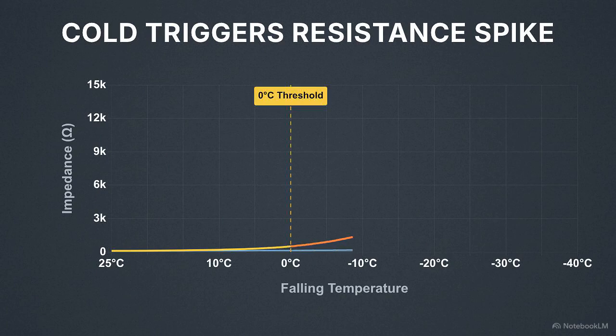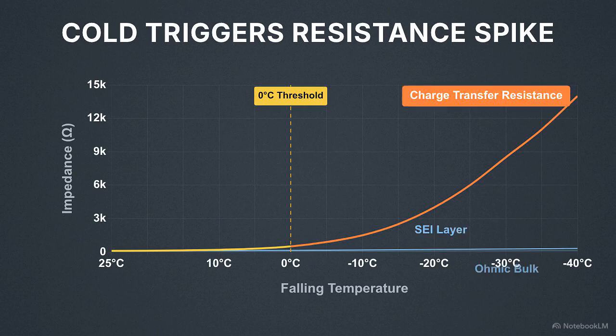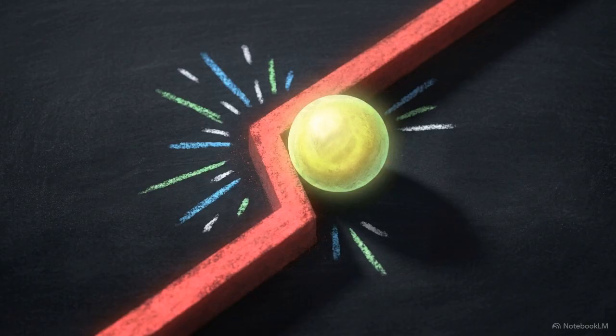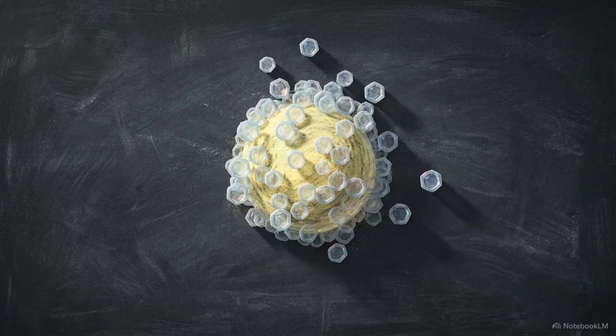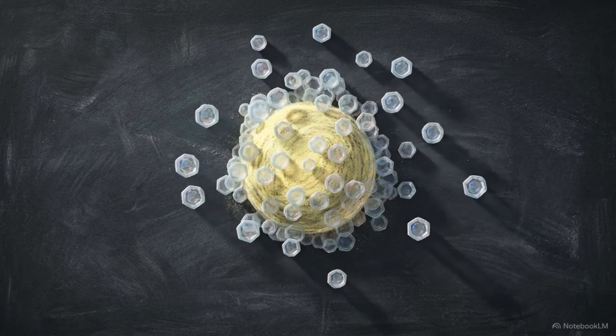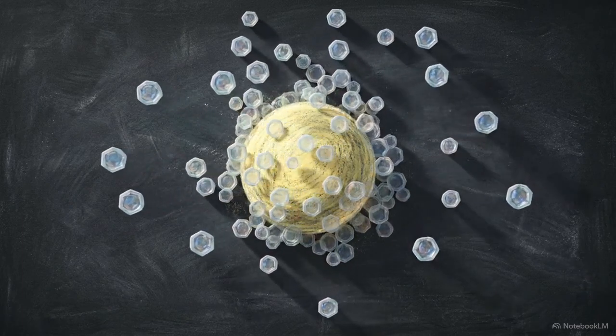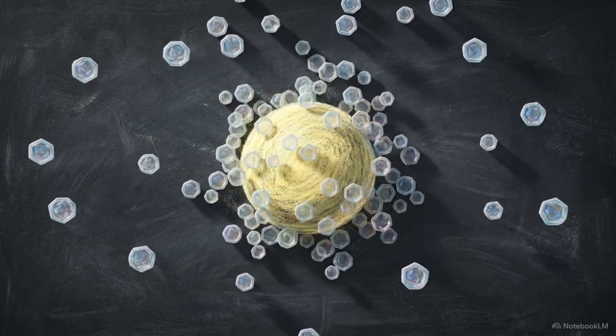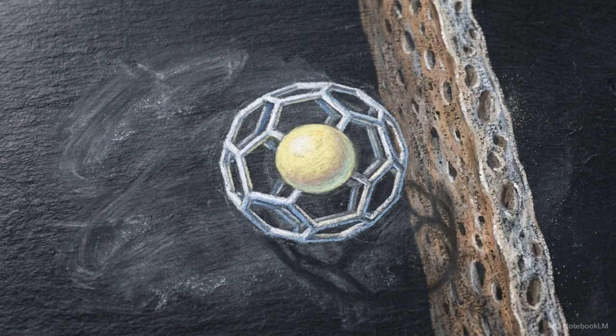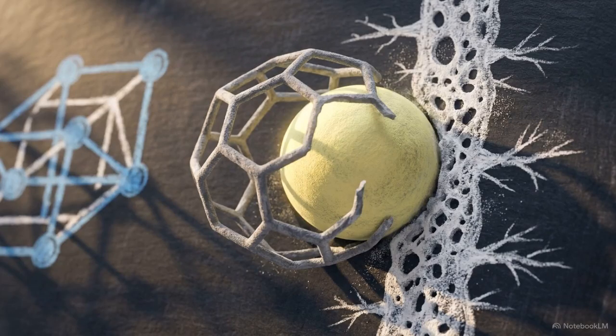Right as we drop below 0°C, charge transfer resistance spikes exponentially, becoming the dominant form of cell impedance. The failure point occurs when ions are forced to cross the border into the solid anode. When a lithium ion travels through the liquid electrolyte, it is tightly bound inside a cage of solvent molecules, known as a solvation shell. Before that ion can pass through the solid electrolyte interface, or SEI, and enter the anode, it must physically strip off this solvent cage.